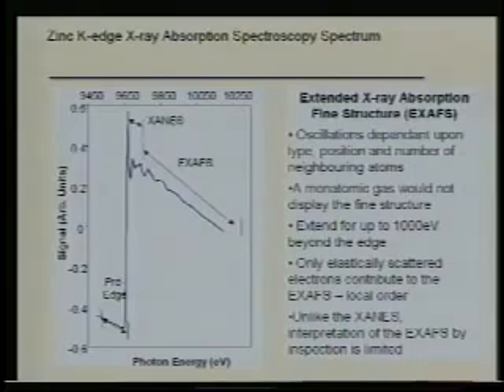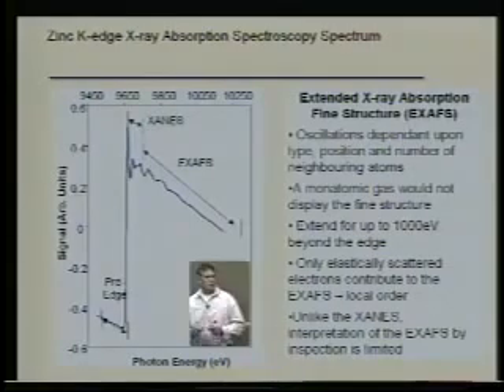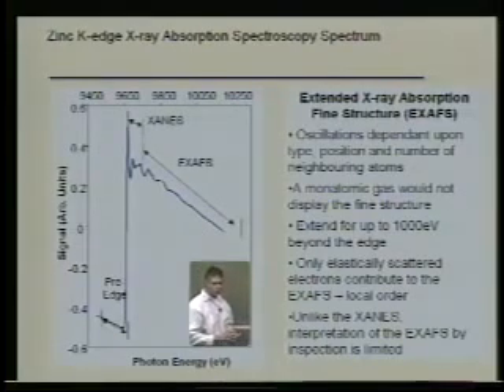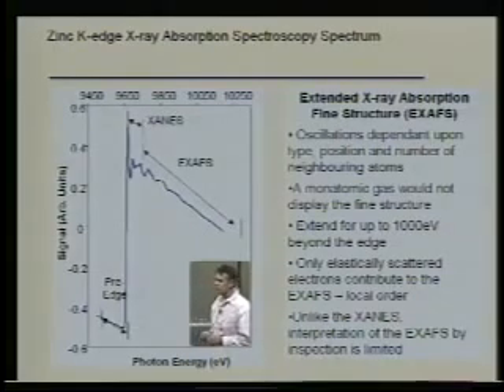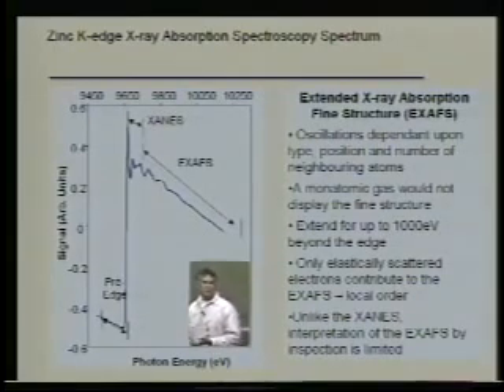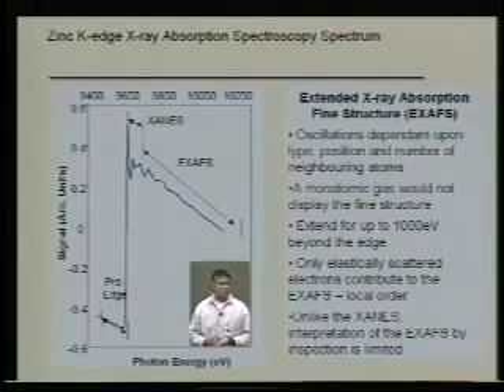Now, these oscillations are independent of the electronic structure, and what's actually happening is the ejected electron interacts with nearest neighbor atoms, and you get constructive and destructive interference because the wave function bounces off the neighboring atoms. So because you're interacting with the nearest neighbor, you're going to get nearest neighbor information. And the XAFS technique is one of the largest characterization fields that uses X-ray absorption spectroscopy because it gives you unique information. It gives you bonding and bond order and also chemical information.